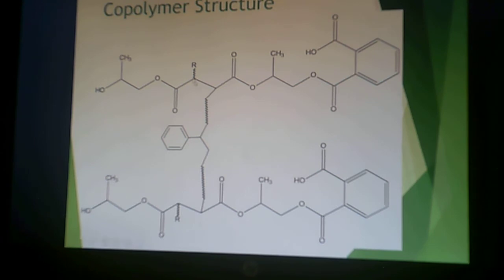So here in the alkyd, we would have had that double bond prior to free radically polymerizing the styrene. So the styrene adds across this double bond and connects chains this way. So here's my little squiggly chain that shows it's going on to another one, and you have your cross-link here that consists of short chains of polystyrene, linking the two alkyd chains together.